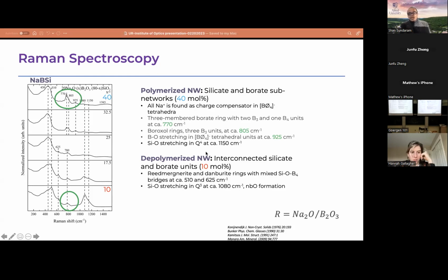And if you look at 805, you are seeing boroxol rings forming at 805. And you can also see there are signatures at 925 centimeter inverse. There are also some overlaps of the signature. Sometimes we have to do a lot of deconvolution to get some quantification going, but we can clearly see a range of bonds, rings, and structures mixed together in this glass. Okay, that's what I want to get across.